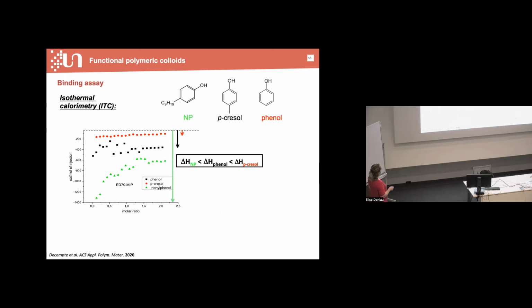And finally, we assessed the selectivity of this MIP using isothermal calorimetry, using the nonyl phenol versus the p-cresol and the phenol. And we could see that the binding is higher with the nonyl phenol than with the others, meaning that the aliphatic chain as well as the phenolic group are both very important and necessary to interact with our network.